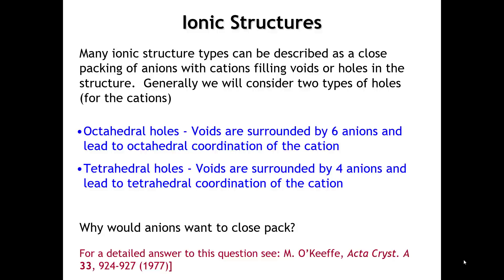There are two kinds of voids in a close-packed arrangement. Some are called octahedral holes because the environment around them is that of an octahedron—six anions surrounding the cation. Other holes are called tetrahedral holes, where the cation is surrounded by four anions in a tetrahedral coordination.